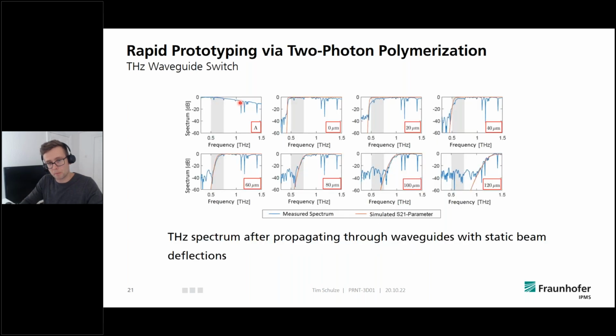And here we can see how it turned out. So what we see here is a terahertz spectrum, the initial spectrum that was illuminated by our source and detected by our system without a waveguide. So you see it starts with a few hundred gigahertz and goes on over 1.5 terahertz. And we don't see a cutoff frequency, nothing, just some small spikes, absorptions from the water in the atmosphere, but that's it. But once I put in my waveguide, we could actually see that there's a cutoff frequency that appears.